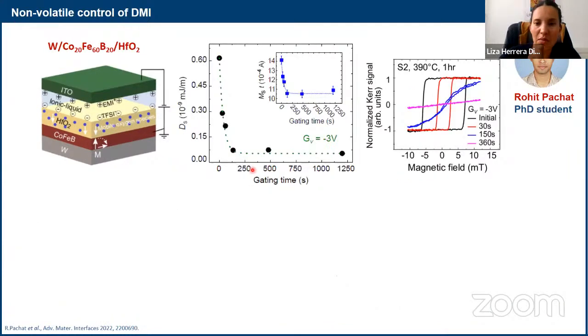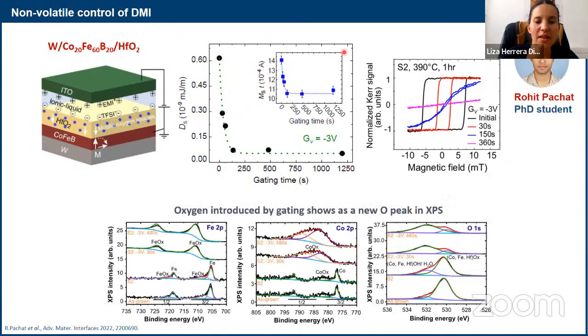Well, in this system, we cannot generate PMA with gate-driven oxidation, but we can certainly kill it. So this is really what we do here. We apply -3 volts, we get oxygen into the system, and then at some point it just goes in plane. We get a similar effect for DMI, it just decreases. We get a decrease in magnetic moment. This is very much in line with an oxidation. This is confirmed by XPS.